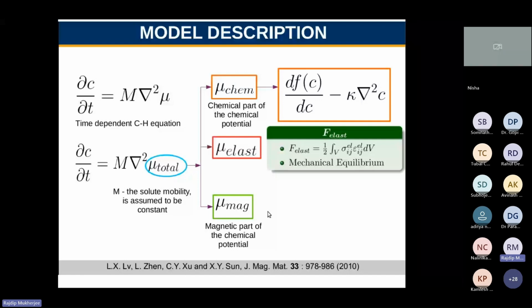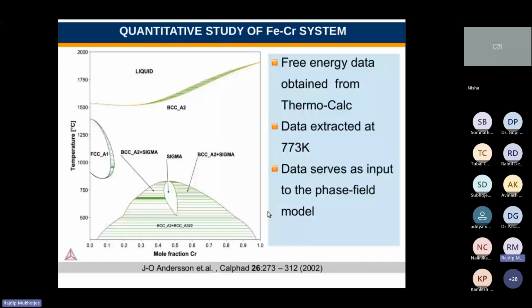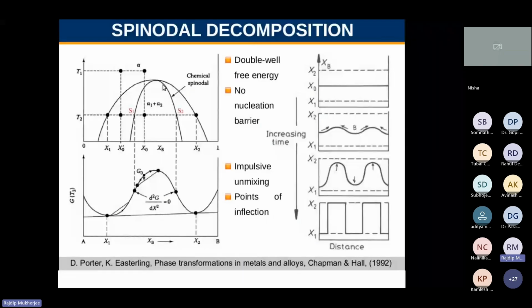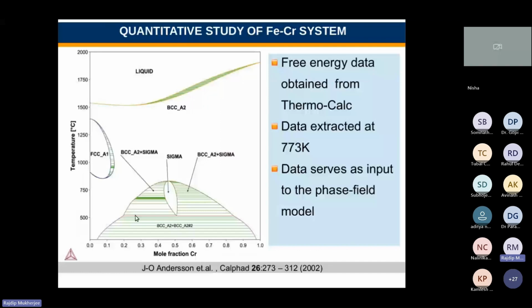Okay, next I'll show you a typical phase diagram, which we get from Thermo-Calc or a CALPHAD approach, and you can see there is a dome which is similar to what I have shown. You see this is the mole fraction of chromium, right? So this is the iron-chromium system, and this is a dome phase diagram which is similar to what I have shown you here. Here it is very symmetric, but in the iron-chromium, it will be slightly different, and there is phase separation into BCC_A2 plus BCC_A2. So this is the iron-rich phase and a chromium-rich phase, it can decompose, right?